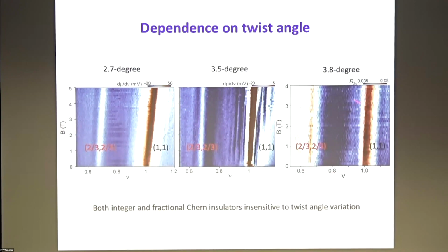Not that much a problem for large angle device, because if you have a certain delta theta in your angle error, in large twist angle, the angle error is not that huge a problem. But in small twist angle device, you can easily see some area is 3 degrees, some area is maybe 2.5 degrees or so. When you do the capacitance study calibrations out of quantum oscillation, do you do that everything is local? At that particular point, yeah. Everything is done at that particular point.